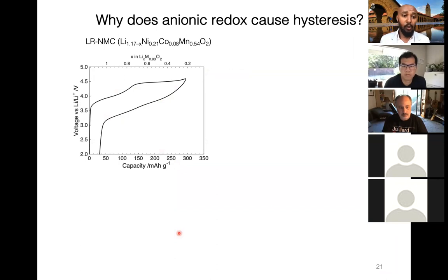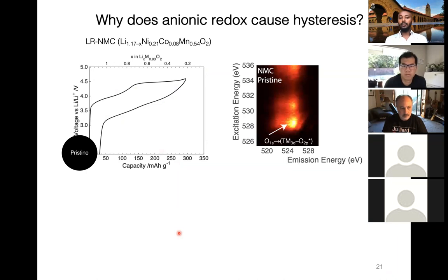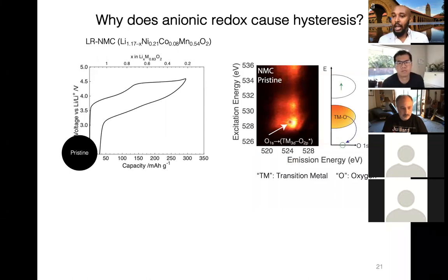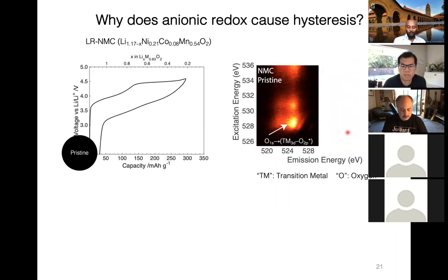In the pristine state, we have a RIXS map that looks like this, where we have a bright feature that's coming around 525 eV in emission energy. And this bright feature is actually coming from excitations or emission processes from the metal-oxygen hybridization over here. But what I would like to draw your attention to is what happens after charging.